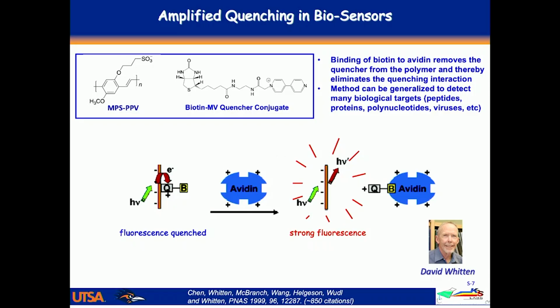But then if you add the protein, which is the partner for biotin, that protein is avidin, what happens is that the biotin-avidin interaction takes over and it basically moves the quencher away from the polymer and the polymer's fluorescence turns on. And so now what you've done is you've made the polyelectrolyte basically a transducer, and the signal that it transduces is the binding event between the protein and the biotin. So you can basically use the polyelectrolyte as a transducer in a signaling event.